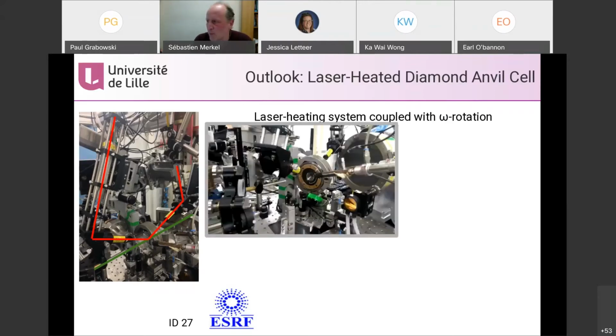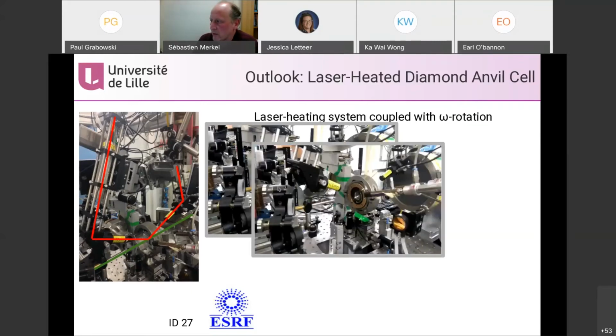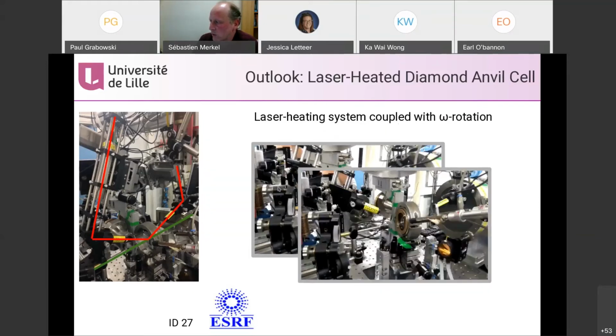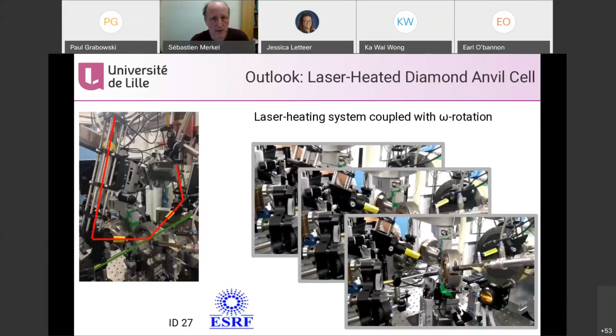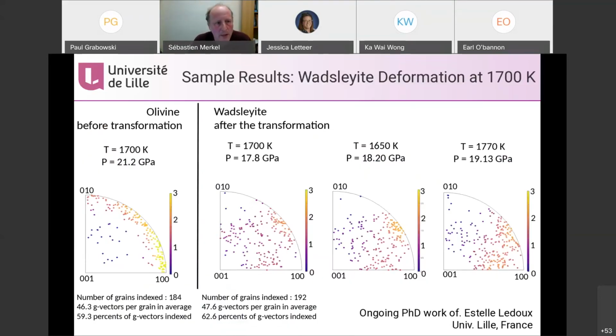So I had a movie, but it wasn't playing very well, so I took screenshots. And so this is our diamond anvil cell on this rotating laser heating setup at ESRF that we measured just before they closed 2 years ago. And so this is a laser heating system and the diamond anvil cell. This is our 2D detector, and the beam is coming from the back. And then we can actually rotate the diamond cell while laser heating. So we can actually collect this type of step scan data while laser heating and while maintaining the sample at a relatively constant temperature.